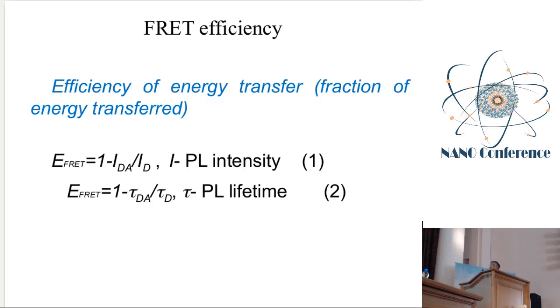So the efficiency of energy transfer in the Forster process can be described by these simple expressions. The first expression is based on the ratio of the intensity of emission of the donor in the absence and in the presence of the acceptor. So this is an energetic relationship. And the second expression is based on the lifetime of the donor in the absence and in the presence of the acceptor. So in principle, these expressions should be equivalent. They should give the same results if we deal with Forster resonance energy transfer.